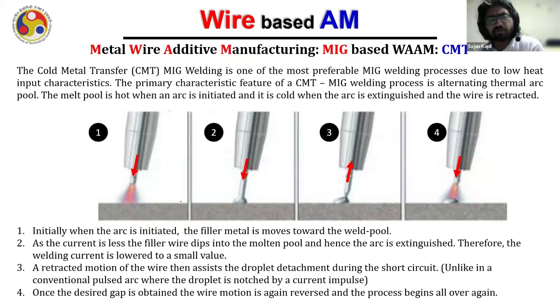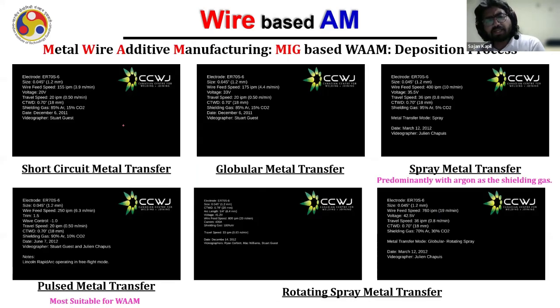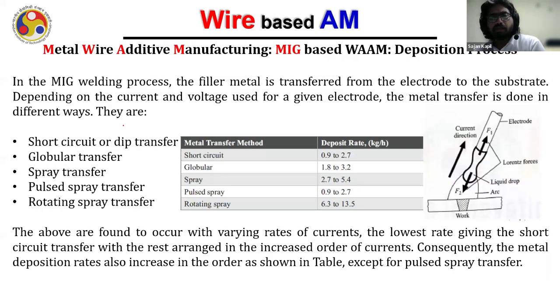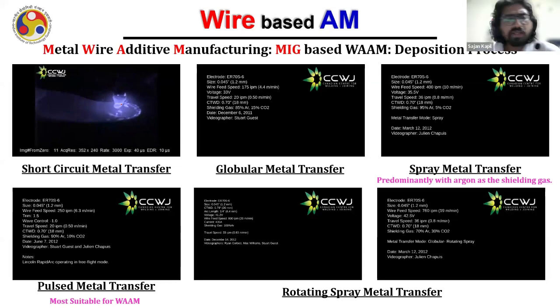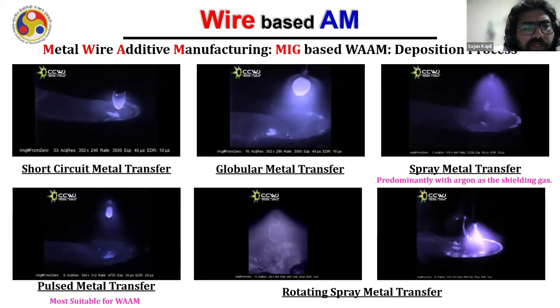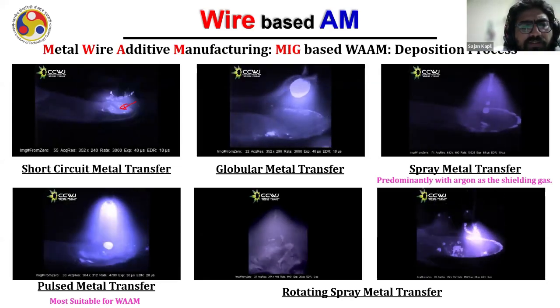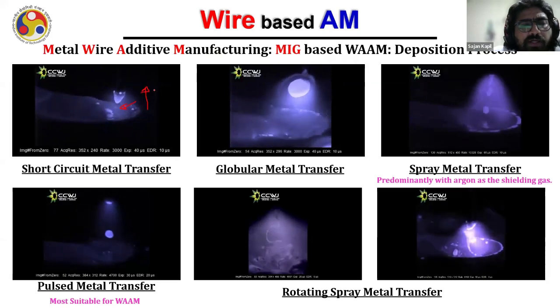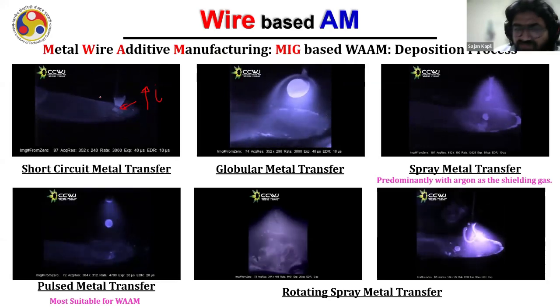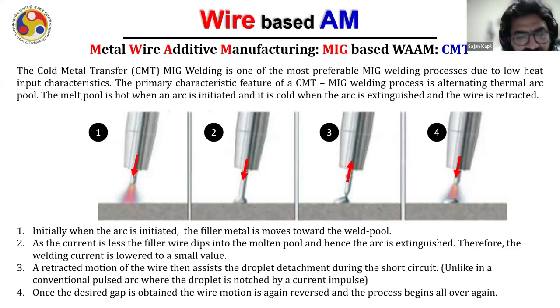Where is the extra heat going in short circuit? They said, "Okay, we will even reduce the heat then in the short circuit." So you see, when the wire touches the melt pool, in the short circuit case, they increase the current, correct, to break it. So they said, why increase the current to break? Instead, I'll pull the wire mechanically.